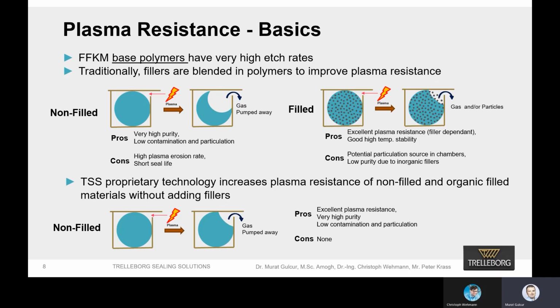So the advantages of filled elastomer materials, obviously the excellent plasma resistance, depending on the filler, obviously. And usually those fillers provide a little bit better high temperature stability, especially dimensional stability. And the concerns for filled material, because of the higher number of ingredients in the formulation, they can have more trace metal content, low purity, or they can just cause particulation in the chamber.